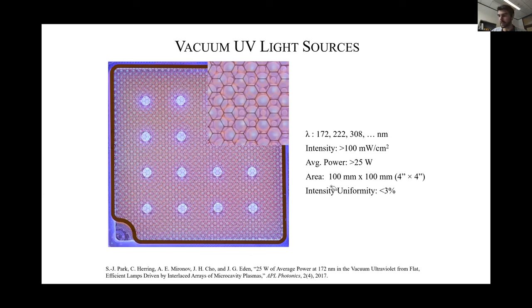So I actually have a real light source here in my hands. So this is a 10 by 10 centimeter light source. You see it's really thin. It's about 4 millimeters in thickness and it produces uniform light. The intensity nonuniformity is less than 3%, meaning that you can actually stack these light sources and illuminate really large areas. You can illuminate 300, 400, 500 millimeter wafers easily using uniform light at 172 nanometers.